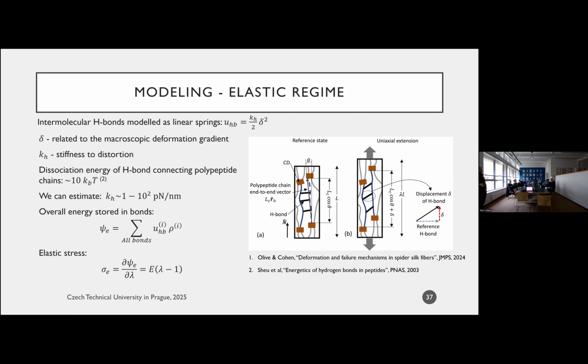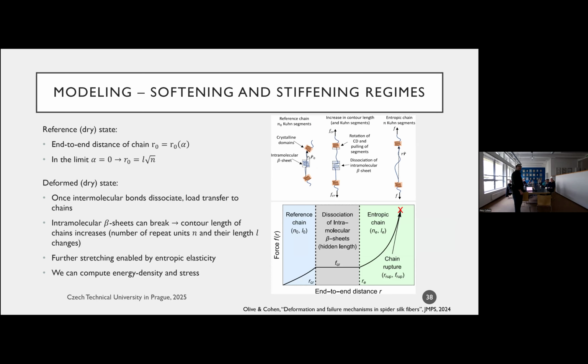After we do this, we can compute the energy of the bonds, and then if we differentiate that, we end up with the elastic stress, right? So that gives us an idea of what the elastic stress looks like. That tells us something about the elastic regime. To capture the softening and the stiffening regime, what we've done is we said, okay, so this is the typical chain, right?